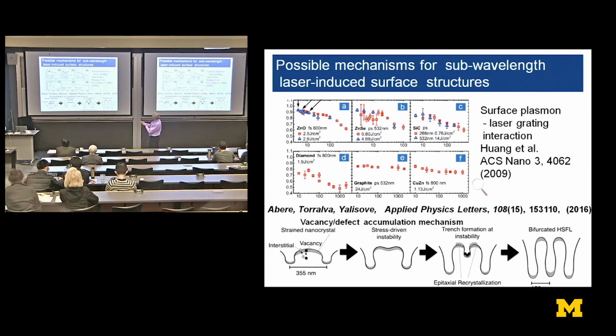And what you can see here, this is the change in wavelength of the wires that are produced, the periodic spacing between the wires actually decreases. In other words, getting more and more high spatial frequency. And as you keep delivering more and more pulses, that wavelength shrinks down, which is the falling curve here. What's happening here is the structure is becoming unstable to spatial modulations driven by the laser field. And this decrease in wavelength here is very indicative of plasmonic coupling,